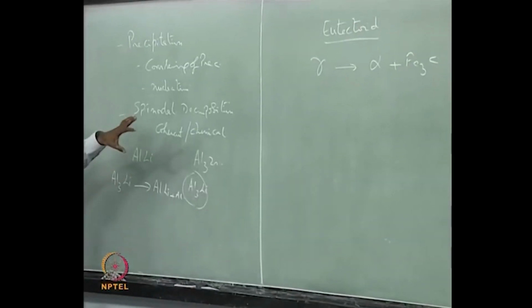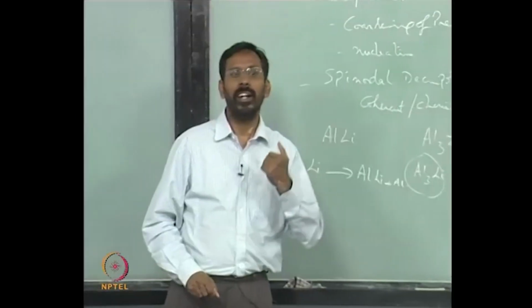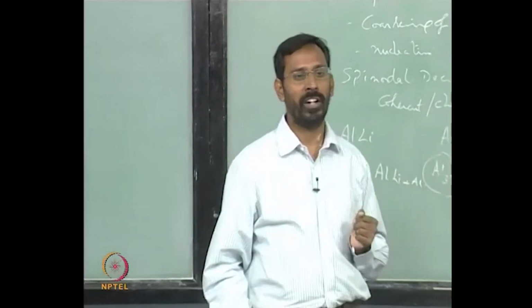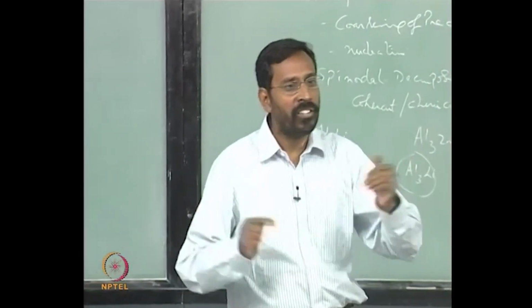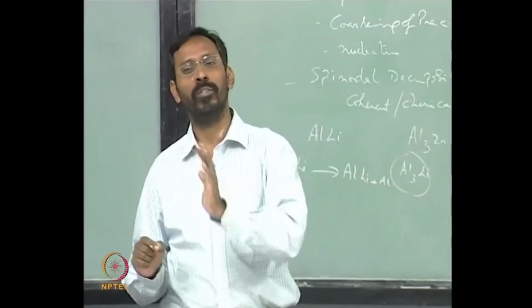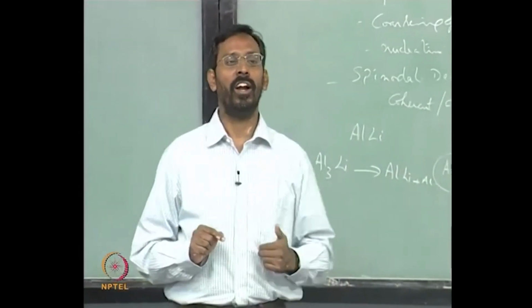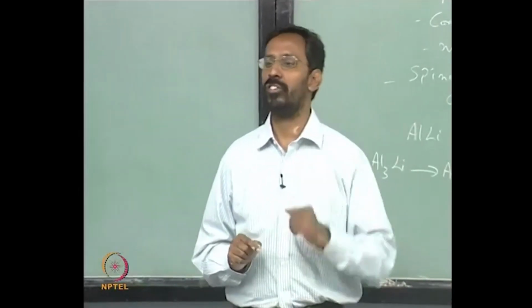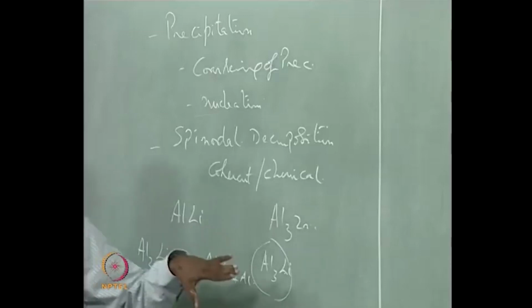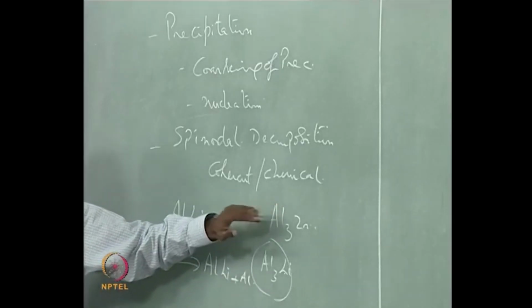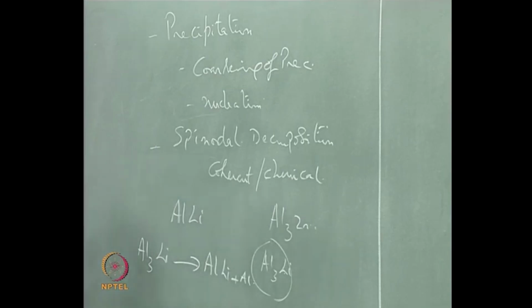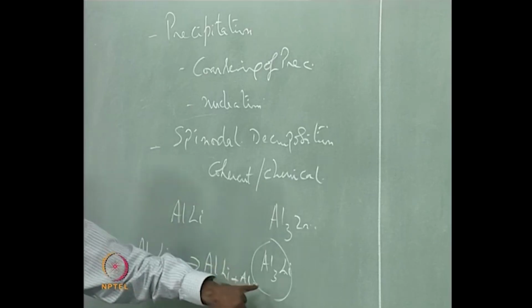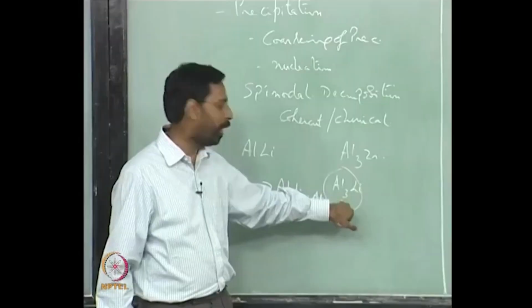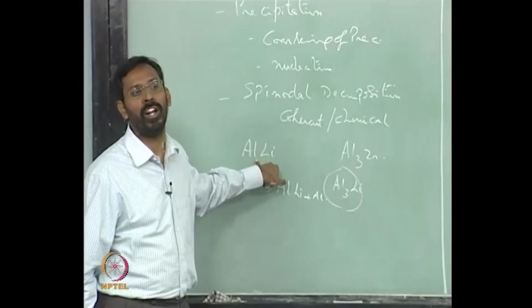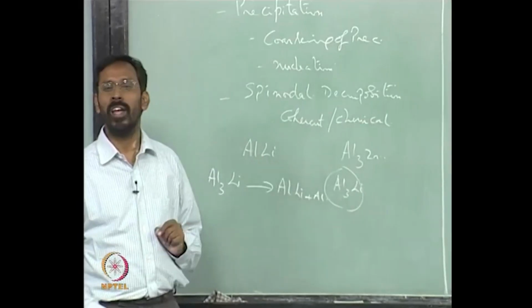Anyway, more importantly, that is one of the reasons why you see the deformation in ordered structures is more difficult. The Burgers vector being larger, the reconstruction of the bonds becomes difficult, so dislocation motion becomes more difficult. So the moment you convert a disordered structure into an ordered structure, you make it stronger. And on top of that, if the bonds are stronger, you will get much higher strength. Anyway, this is all related to precipitation. The reason I had to come to this is that this kind of metastable phases can come out, provided a stable structure is more difficult to nucleate, and you have innumerable examples of it.